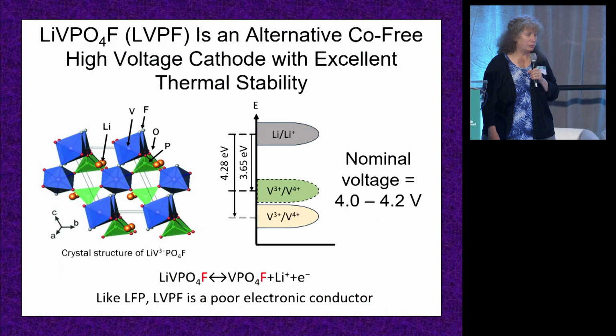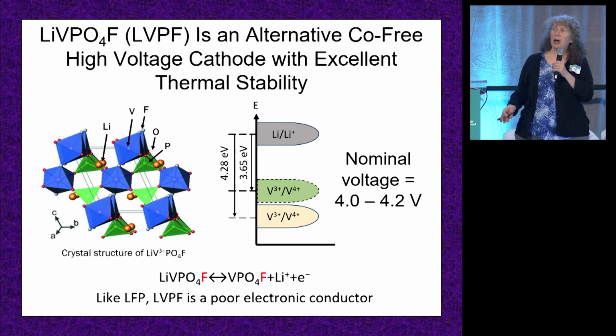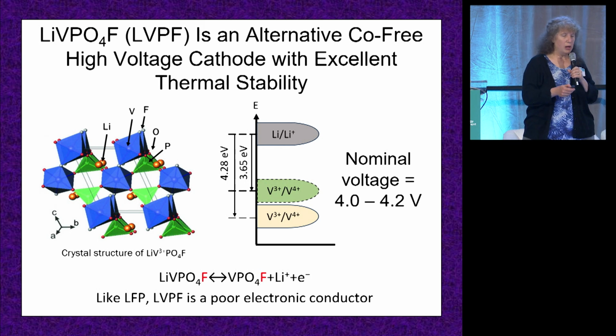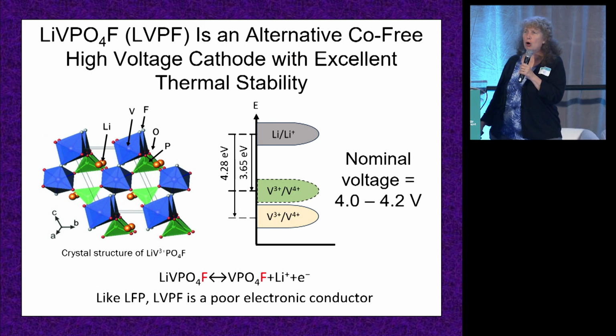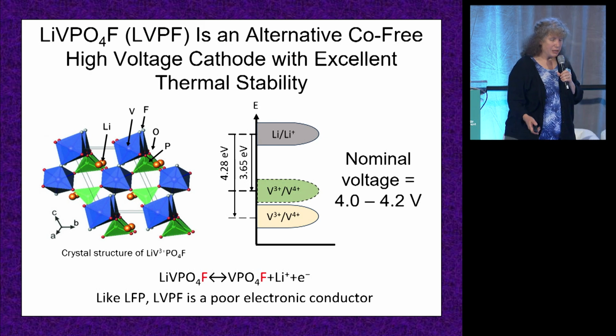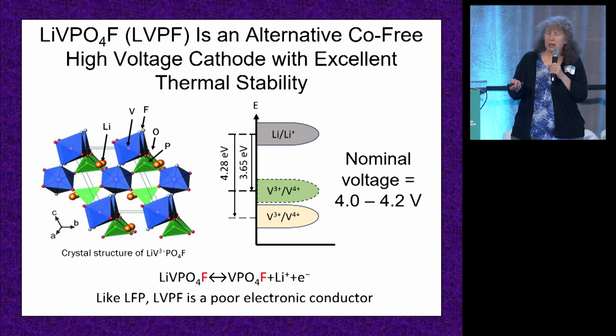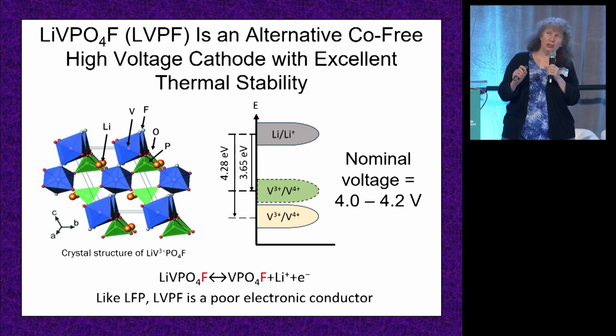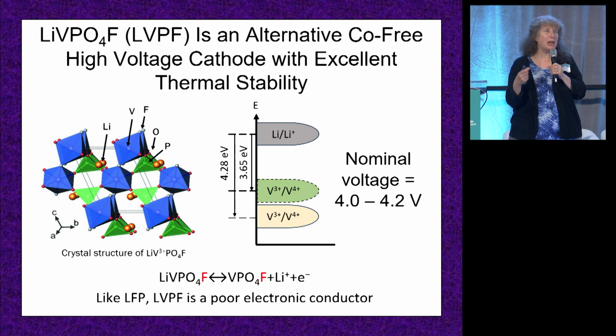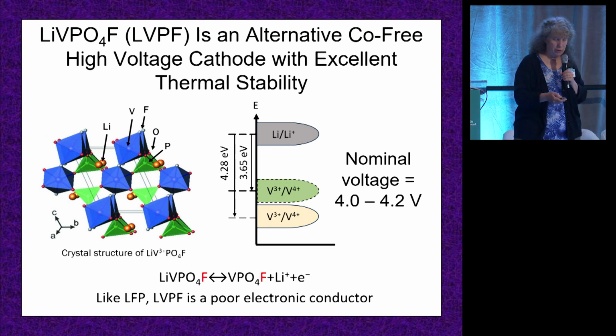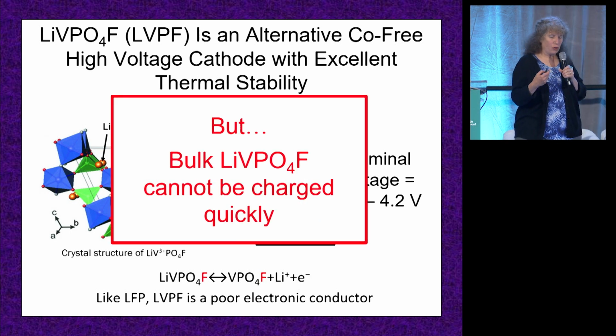Okay, so what are we going to do? We are moving to a next generation material called lithium vanadium fluorophosphate. I'm just going to call it LVPF. And this is an alternative cobalt-free cathode. It is very similar to lithium iron phosphate. Not quite as cheap because vanadium is not as cheap as iron, but it is much higher voltage. Otherwise, it has many of the same properties as lithium iron phosphate. So it's a great, interesting material, except that in the bulk, it is not fast at all.